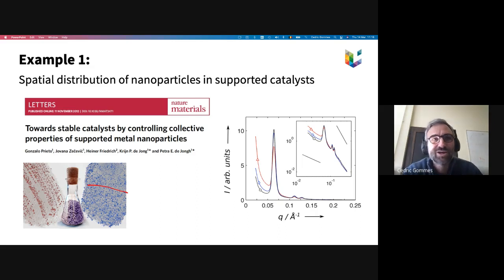So it means that in a chemical reactor, you have about as many of these grains as you have water molecules in a dewdrop. So people are always obsessed about how representative this characterization is. And that's where small-angle scattering plays a role, because when you do small-angle scattering, you are characterizing a macroscopic amount of sample, say of the order of a few milligrams.